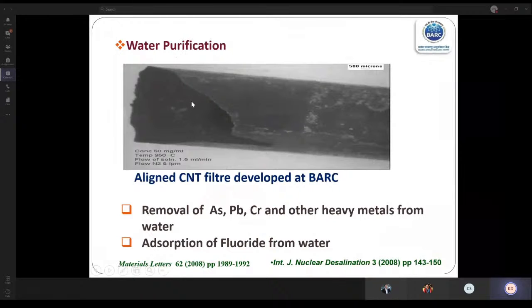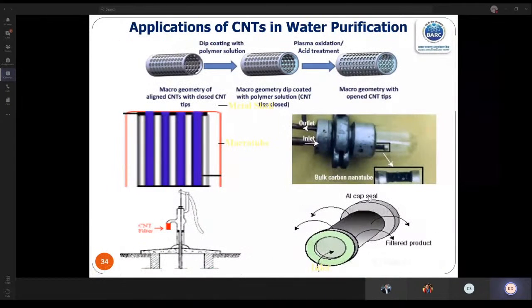Now coming to application in water purification. For all these applications, we require very high surface area of carbon nanotube, and it absorbs the heavy metals or even the fluoride from the water. Here we developed a freestanding structure where the carbon nanotubes are in the radial direction of this tubular macro geometry. These are aligned carbon nanotubes. The philosophy is that the water should flow through that and come out from the wall. While coming out, only water will come out, and the heavy metals and the fluorides from the water will get absorbed. So this is a typical module, means we can make this kind of geometry and we can fit them under a hand pump or other water sources, wherefrom we can get the pure water.